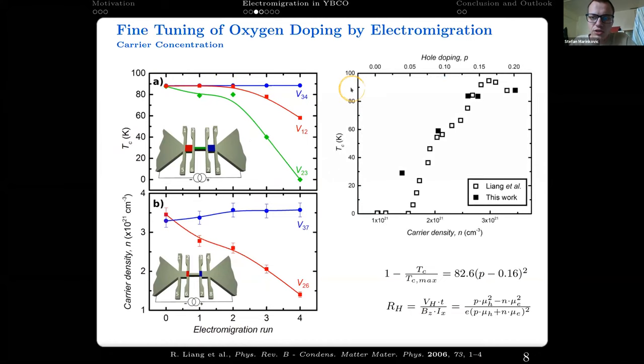We compared this to some other experimental results by Liang et al. and have shown good overlap. There are some considerations to be taken, like they measured in single crystals at room temperature, while this was measured at lower temperature in our devices, but still there is a significant overlap, which shows that this could be useful to tune our devices.